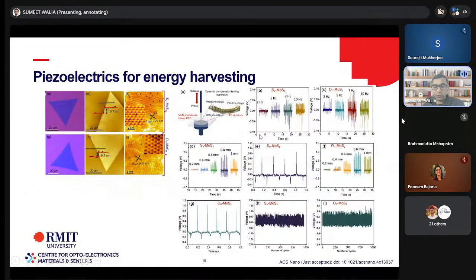Then we moved on to study the effects of these sulfur vacancy defects and oxygen passivation on the piezoelectric properties of molybdenum disulfide as well. So again, we performed a series of tests using AFM as well as devices prepared on a PET substrate and subjecting them to different mechanical bending cycles.